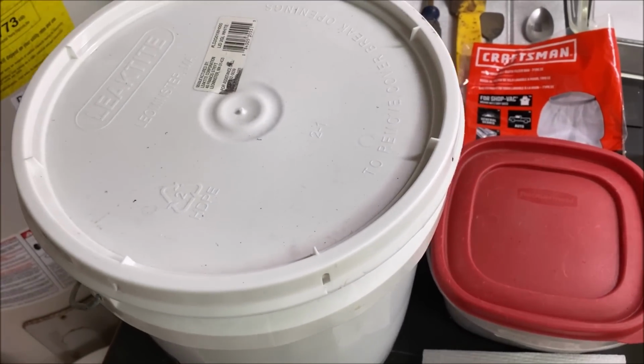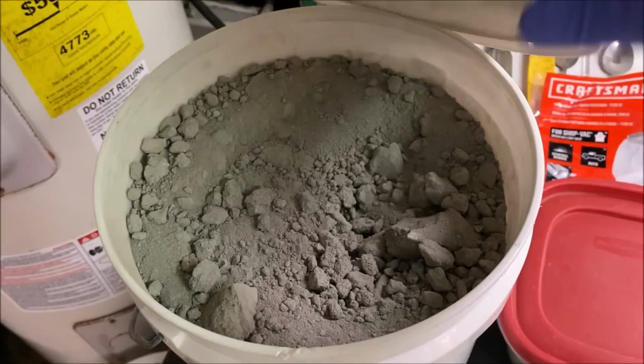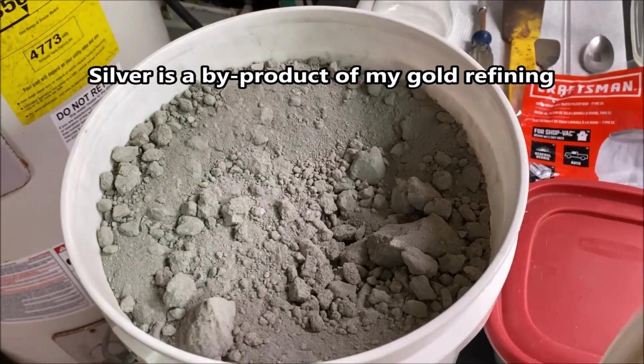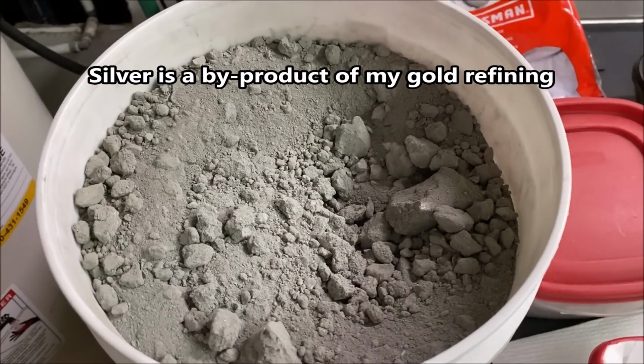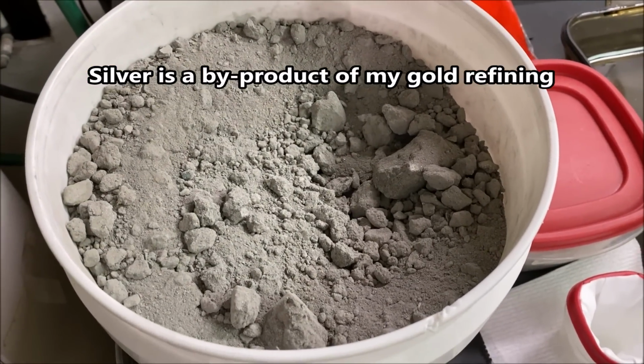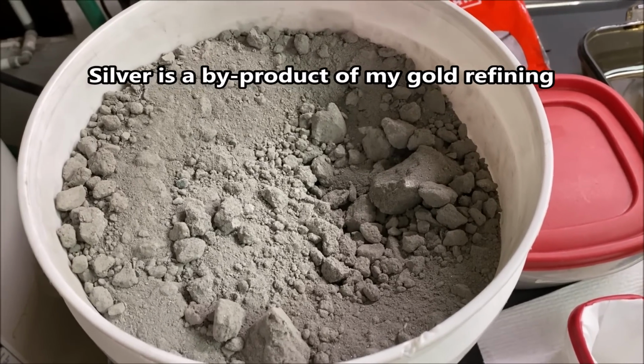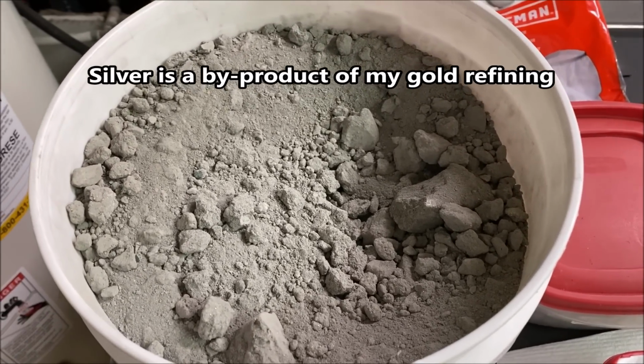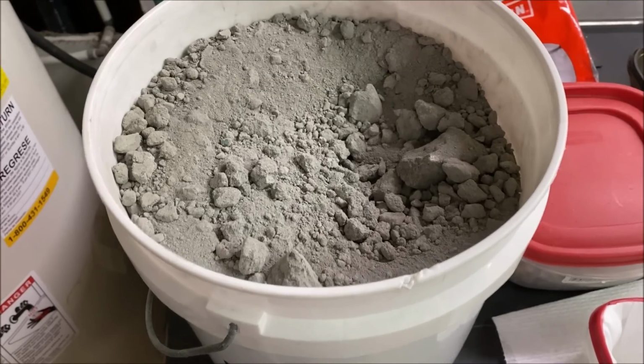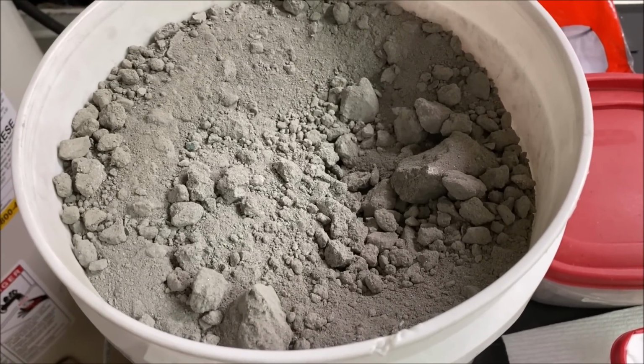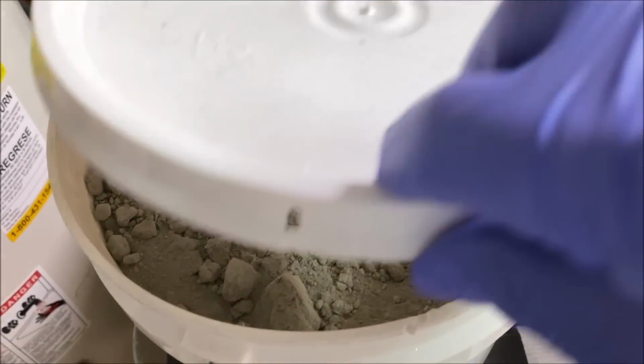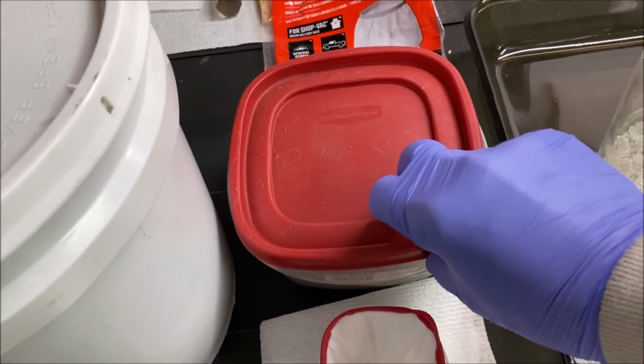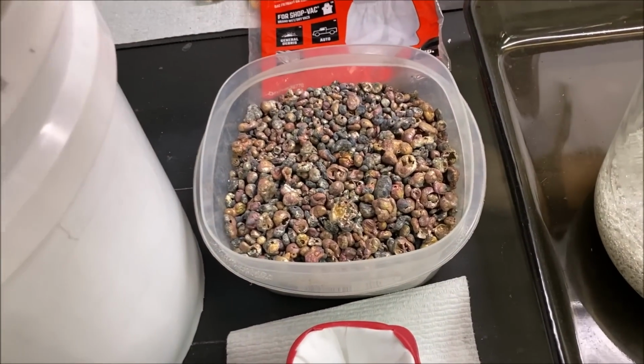When I refine gold, I use sterling silver to inquart the gold. Then I pull the sterling silver back out with hot dilute nitric boils. I recover that silver and then cement it on copper. And this is a 2.5 gallon bucket full of cement silver. And then what I do with that is I melt it and form these granules.